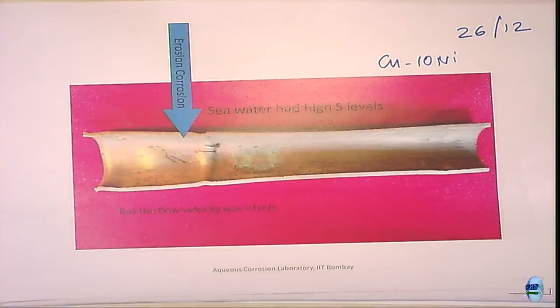And this heat exchanger is quite far away from the cooling tower, okay. So the flow velocity of this is lower. When the velocity is less than 1 meter per second and it fails, you do not really look at erosion corrosion as a primary mechanism, right? You see now, you can go up to close to about 2 meters per second of flow velocity if it is a copper nickel alloy.